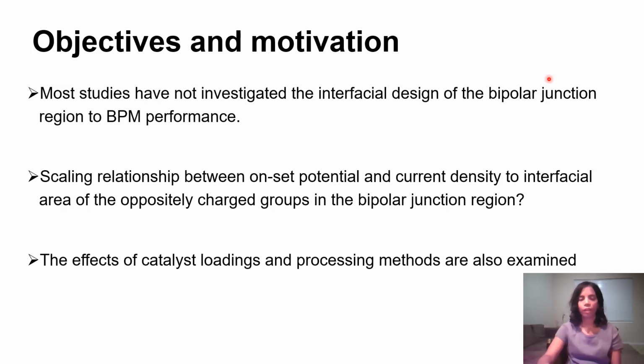In this work, I have prepared micropatterned bipolar membranes, and I have calculated the scaling relationship between the onset potential and current density of the interfacial area of oppositely charged groups in the bipolar junction region. The effect of catalyst and processing methods are also examined in this study.